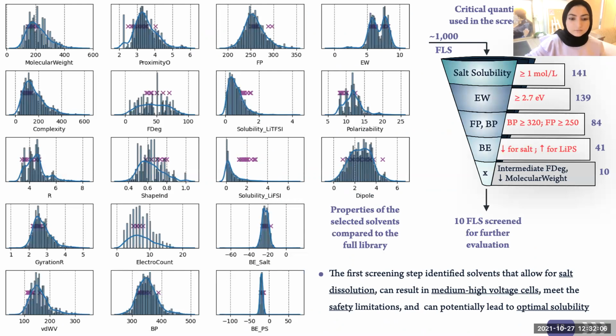So in this step, after we computed all of the properties of interest and built our database, we defined critical quantitative limits for the most important properties to be considered in the next step. In the first step of the screening process, we down-selected around 141 solvents from the library of 1,000 fluorinated solvents based on the salt solubility. And for this, there is a lower limit of 1 mole per liter for common salts of lithium TFSI and lithium FSI.